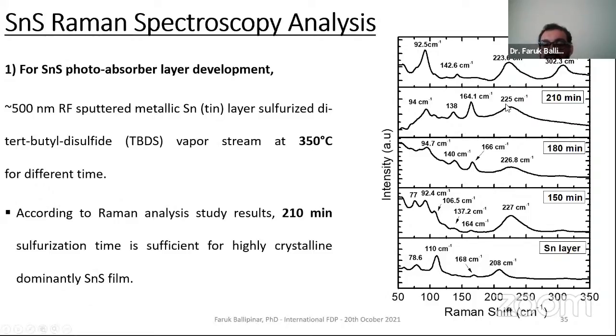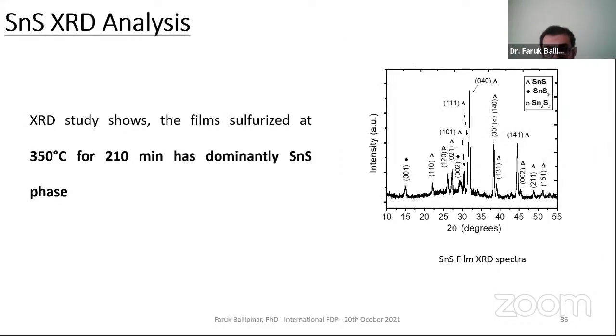So basically, these charts give an idea of which temperature provides the dominant tin sulfide, after what time it provides highly dominant tin sulfide, and after what time the secondary phases have already started to form in the entire film. So based on the Raman analysis, 210 minutes is the optimum sulfurization time for the 500 nanometer RF sputtered metallic tin layer at 350 degrees to form a highly dominant tin sulfide film. Again, the XRD spectra show there are secondary phases, but the dominant tin sulfide phase is available in the film.